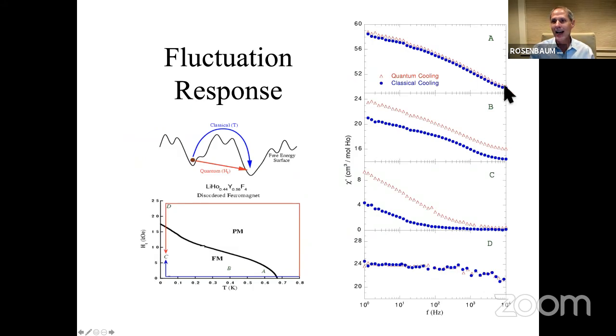What I'm plotting here now is the real part of the susceptibility rather than the imaginary part of the susceptibility, because I know that the ground state here is a divergence of this real part of the susceptibility. This is as a function of frequency again now from 1 hertz up to 10 to the 4th hertz. It doesn't go there immediately. It takes time to diverge because of the competition between the ferromagnetic and anti-ferromagnetic bonds. So it's a little glassy in that sense.